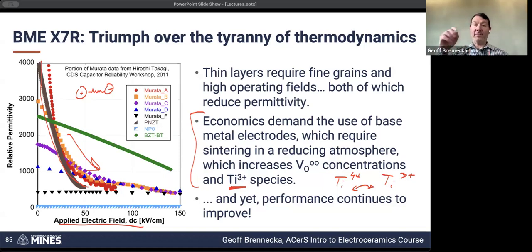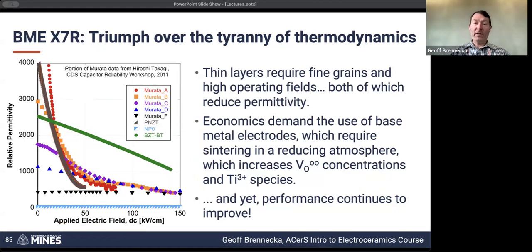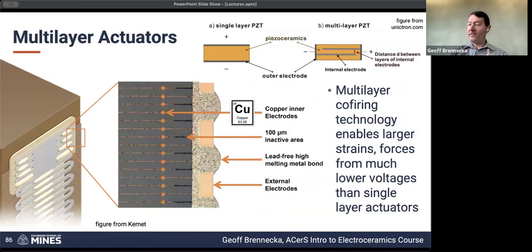So you've got that capacitor with a resistor in parallel with it, and you just reduce the amount of resistance of that parallel resistor. So now you're able to leak more current through it, which is not at all what you're after. So we try to avoid low partial pressure of oxygen because that can cause problems with titania and with oxygen vacancies. But we need to sinter at low PO2 to keep the nickel reduced as nickel metal. So that's a whole other challenge, but it's one that's largely been tackled successfully.